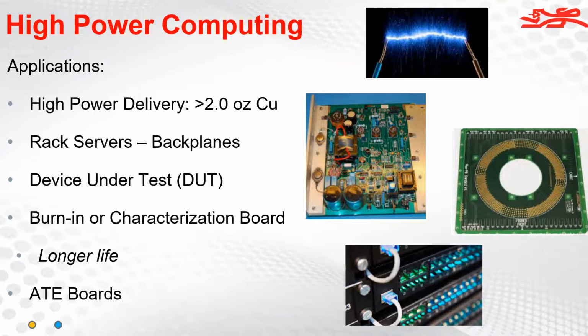And so this type of material has the ability to manage and handle the heat much better. And so they can get a lot more cycles out of those boards and the cost is then significantly reduced in those types of devices. So burn-in boards or characterization boards, ATE boards, this material will give them the opportunity to extend the life of the product overall. Lead-free phenolics, so epoxy-based lead-free phenolics, the more heat they see, they tend to get more brittle too. I mean, that's just the nature of the resin chemistry.